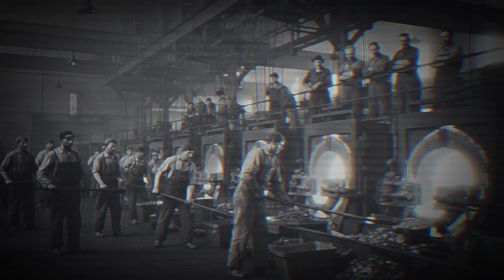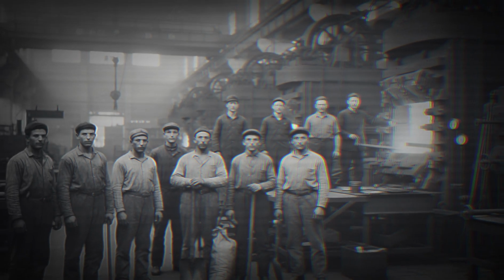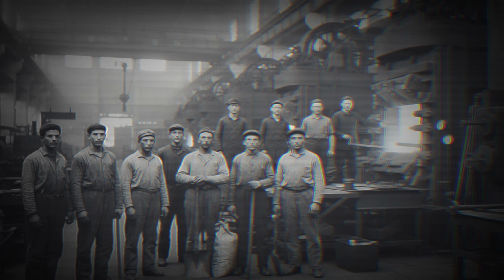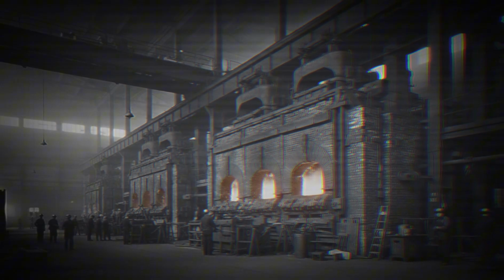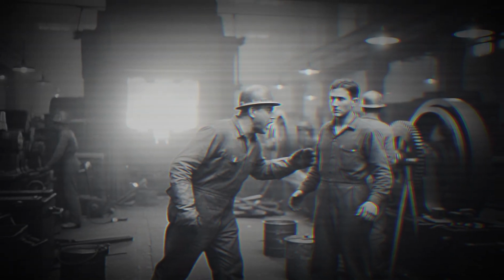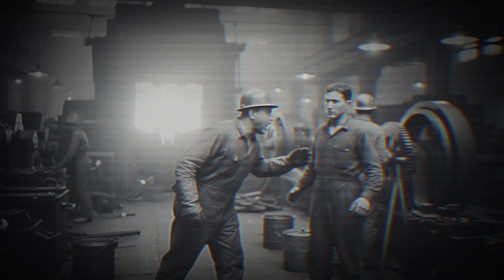At each end of the furnace is a port, an opening through which fuel and air enter. Underneath each port is a large chamber called a regenerator, also called a checker chamber. These chambers are filled with a stacked lattice of refractory brick. Here is the cycle. Fuel gas, in early mills producer gas derived from coke, later natural gas, and preheated air enter through one port. They mix and combust in the furnace chamber above the steel bath. The flame passes over the bath, heating it. The exhaust gases then exit through the opposite port and pass down through the opposite regenerator. The heat from those exhaust gases is absorbed by the brick lattice in that regenerator.